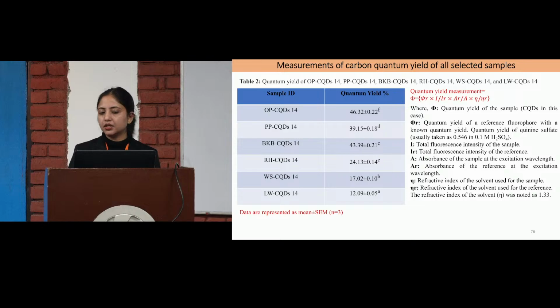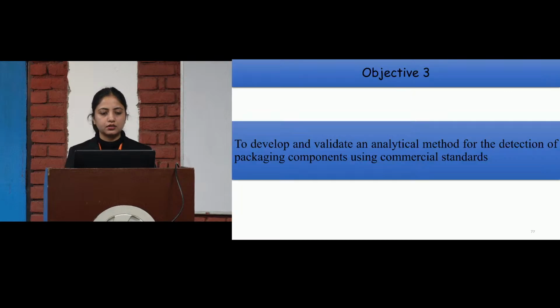As you can see, the quantum yield is highly related to the carbon content of the materials. As we discussed in the EDS, we analyzed the elemental composition of these materials. The onion peel has the higher carbon content, so we got the higher quantum yield for the onion peel derived CQDs.